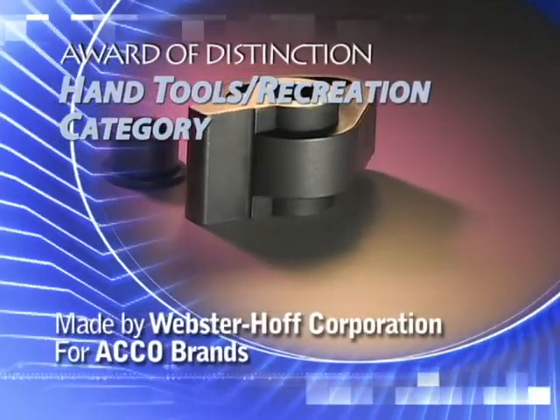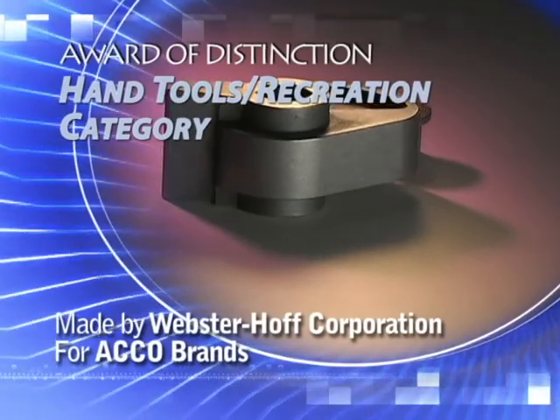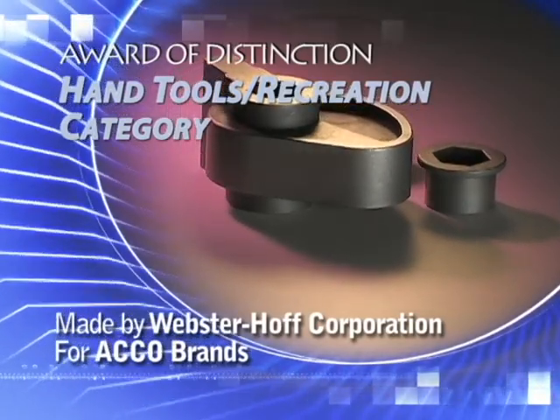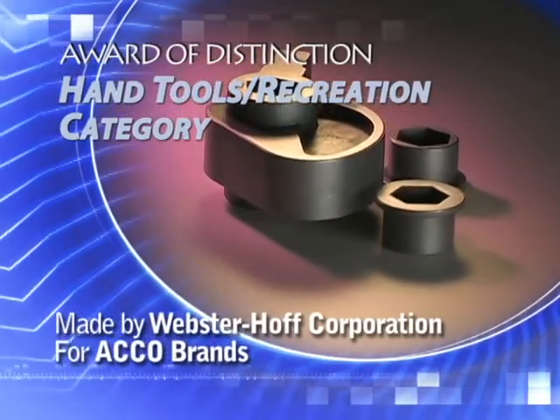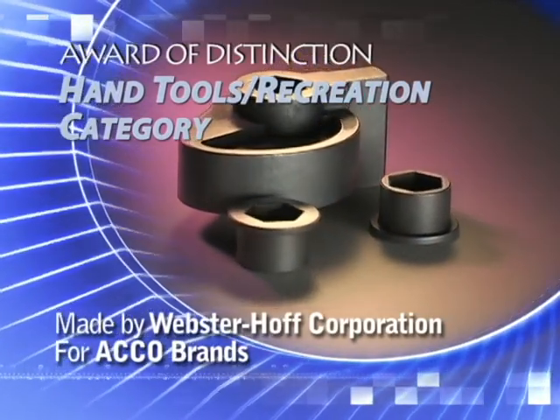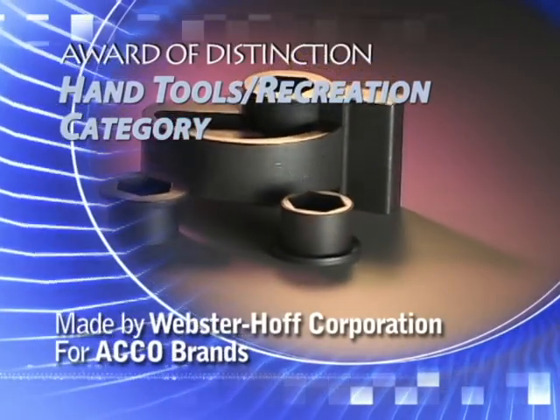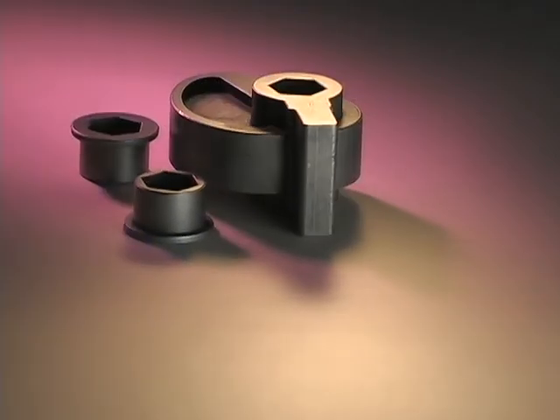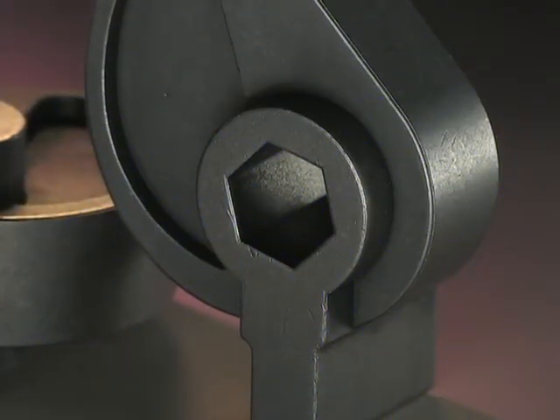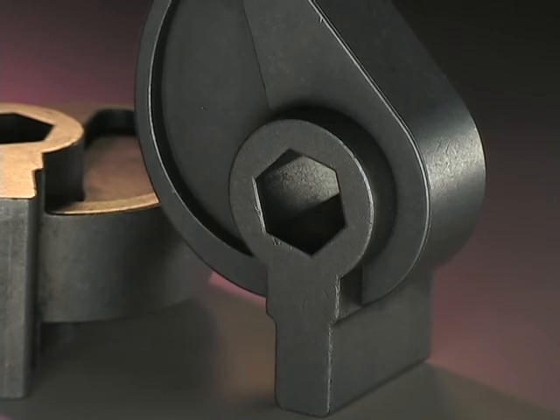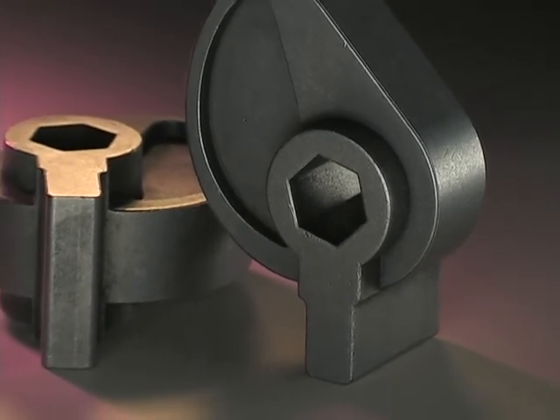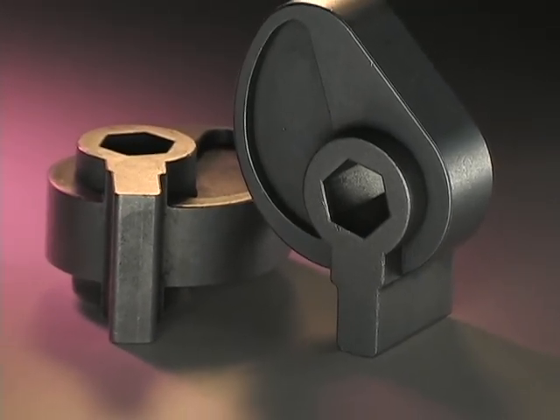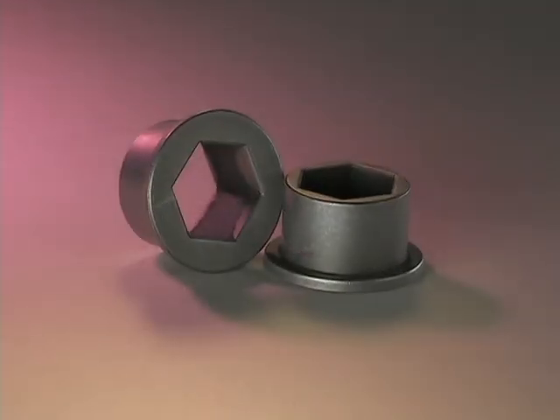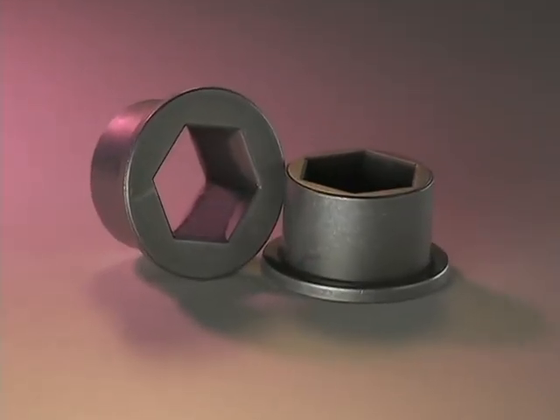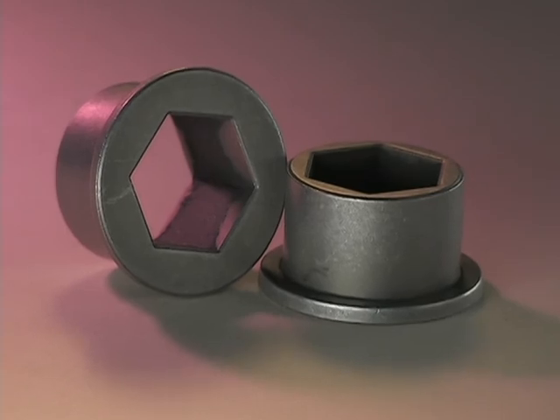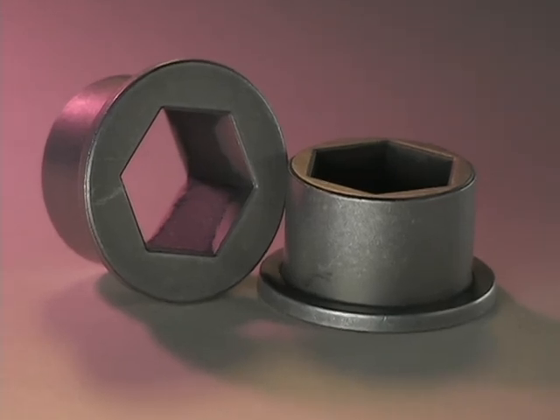Webster Hoff Corporation and its customer, ACCO Brands, have received another award of distinction in the hand tools recreation category for a PM sinter-hardened steel cam and bushing used in a manual paper hole punching machine. The cam transfers power to the cutters, and the bushing supports the shaft. Both parts are formed to a density of 6.7 grams per cubic centimeter and have an ultimate tensile strength of 120,000 psi and 27 HRC apparent hardness.